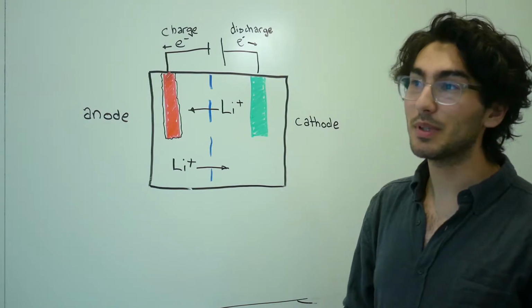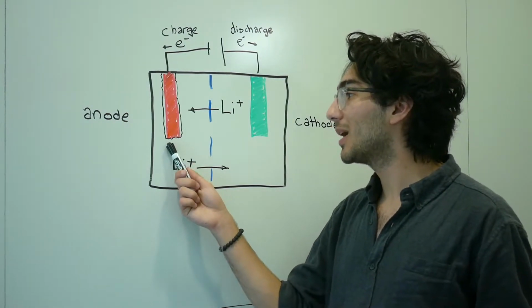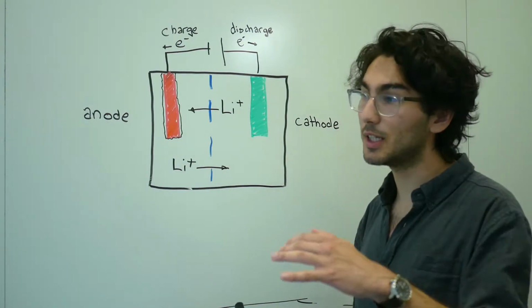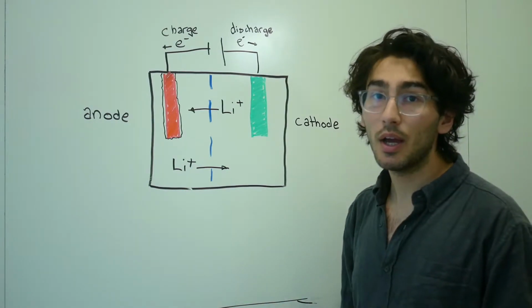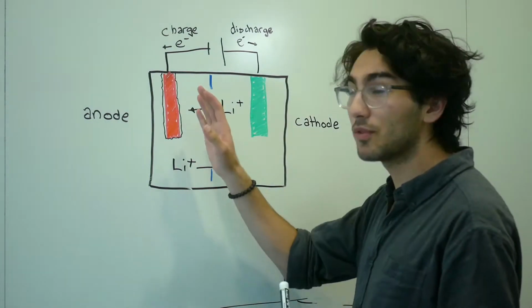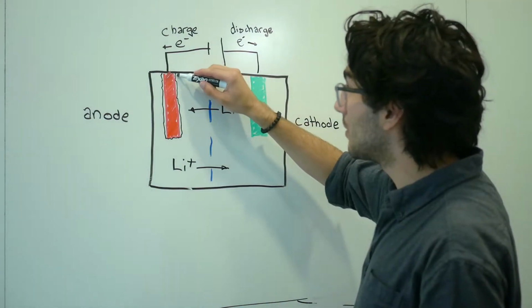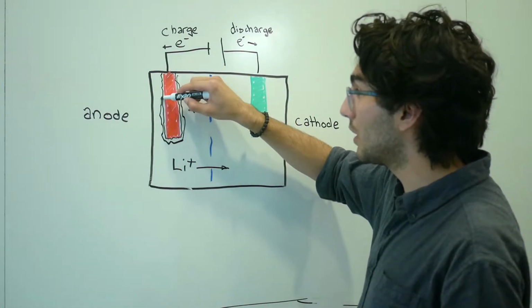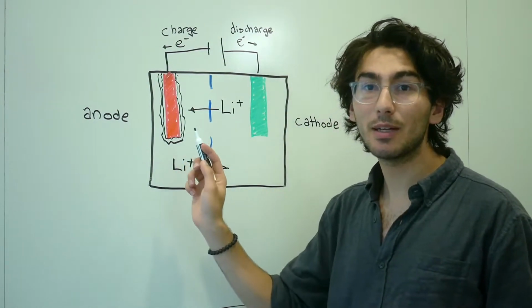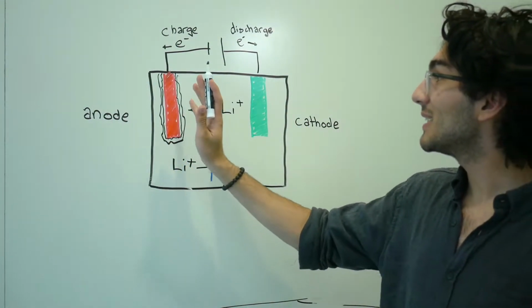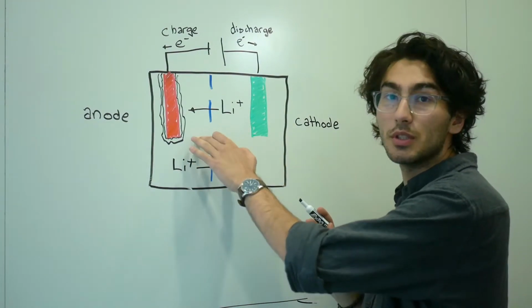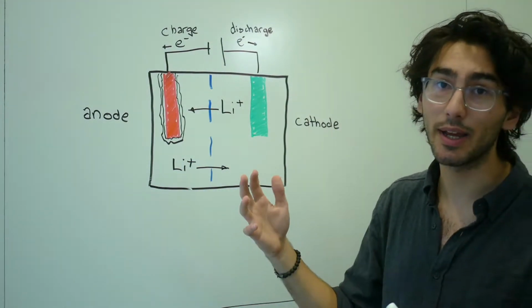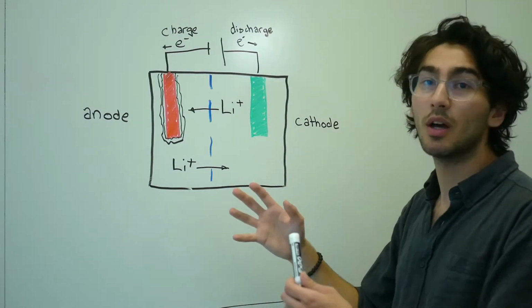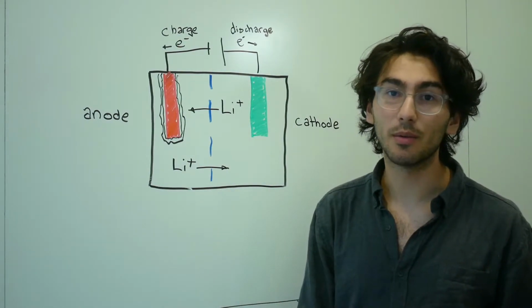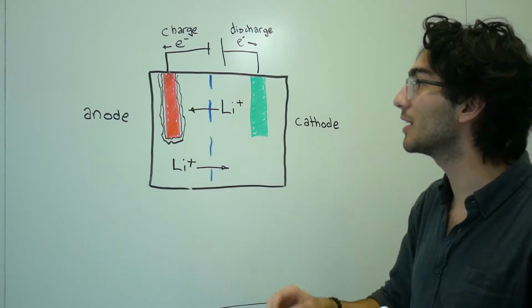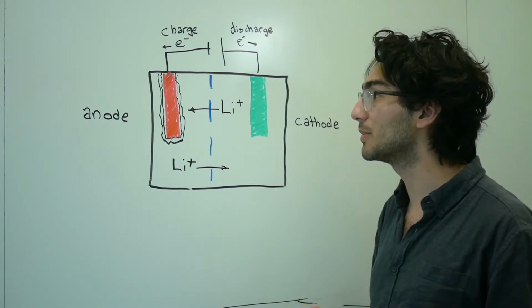This isn't really something that can be avoided, but over time, this layer can grow even more and keep degrading your battery health. The issue with this SEI layer that forms around your anode is that as you get more and more layer formation, you're trapping these lithium ions inside that SEI layer, and they can no longer be used in this transfer process between the anode and the cathode. And what that does is, of course, lower your battery health a bit, and so over time, as you have this layer growth, you're going to lower your battery potential.